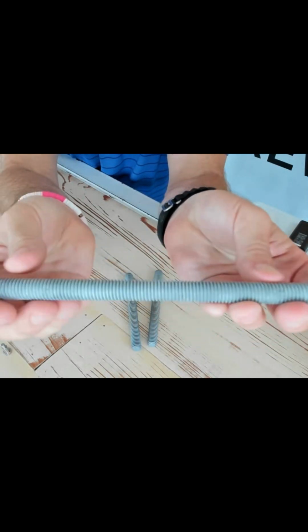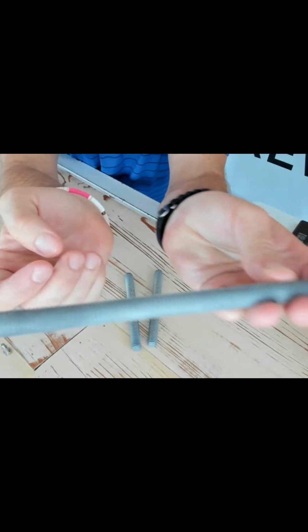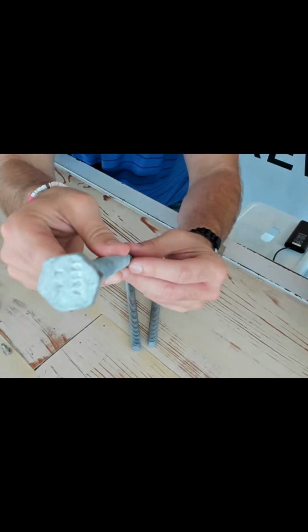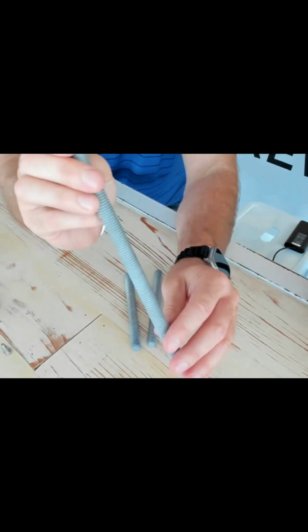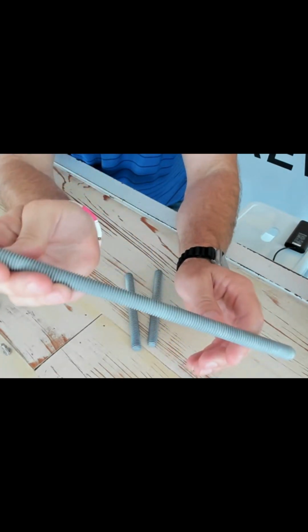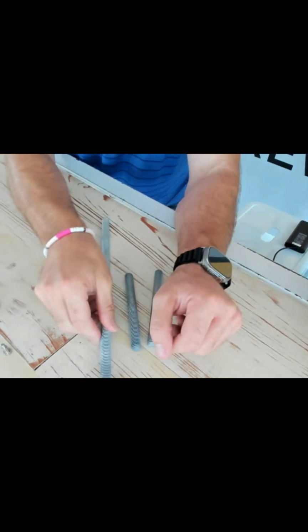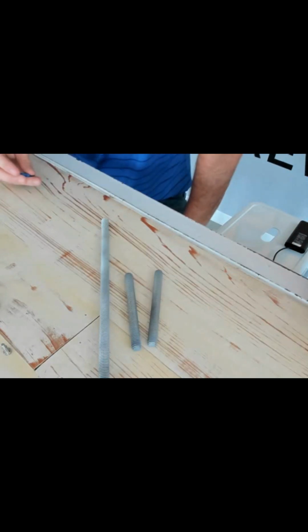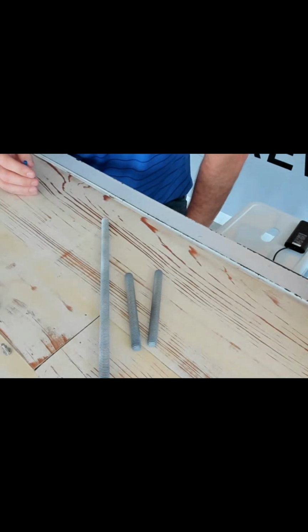When you put zinc on the outside of the fastener, that is the sacrificial element that will corrode prior to the base metal of the bolt. So the zinc is the anode in the whole corrosive circuit there, so when you put that thick zinc coating on, it's going to have to corrode before the bolt does. So it will corrode over time, and the zinc will eventually leave, but it does buy you a lot of time before that corrosion ever attacks the base material of the bolt. So zinc is a very common sacrificial metal that's used as a coating for corrosion.